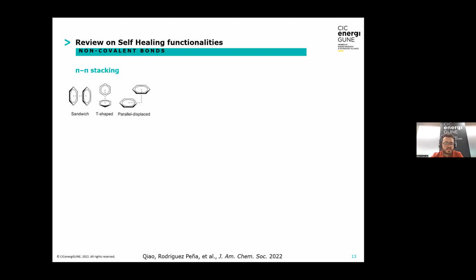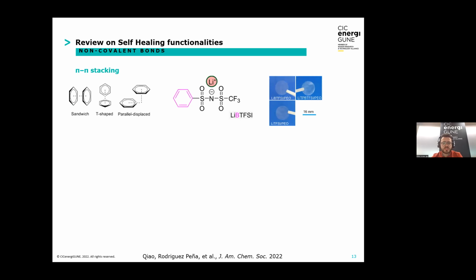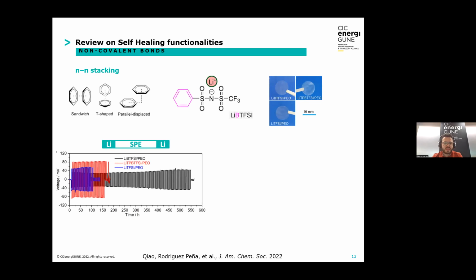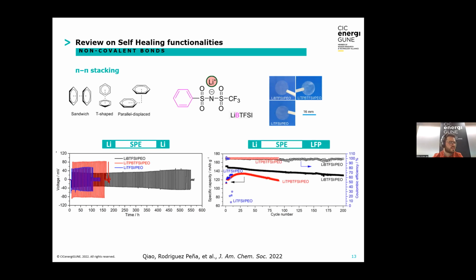So to the best of our knowledge, polymer electrolytes with metal electrodes usually don't comprise this type of self-healing technique due to the reaction of the aromatic rings and the metal electrodes. However, there is an interesting approach in the literature that uses pi-pi stacking in the lithium salt anion. So this allows to increase the lithium transference number and increases the lithium stripping and plating lifetime of the battery compared to, for example, an LiTFSI lithium salt, and also increases the cell lifetime in full cell with a lithium